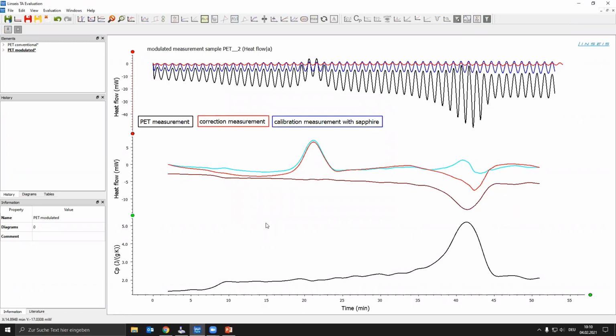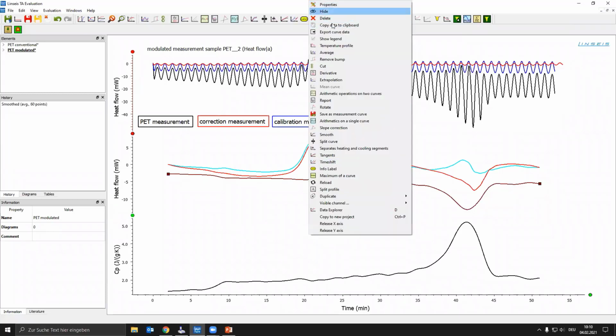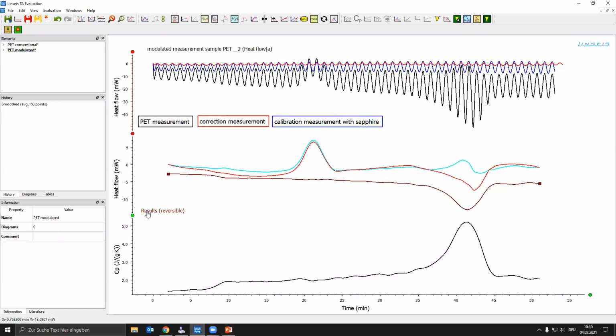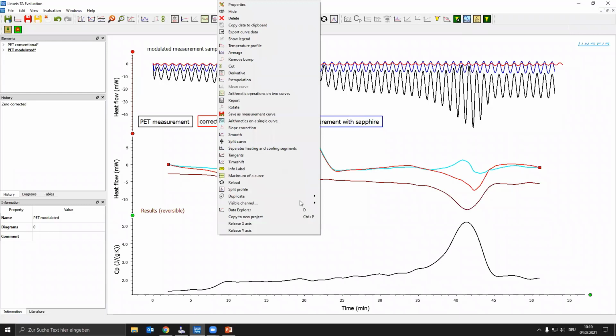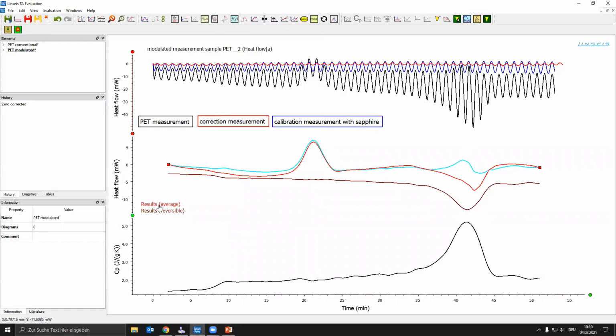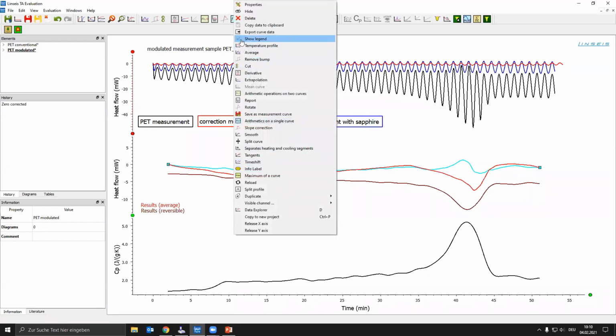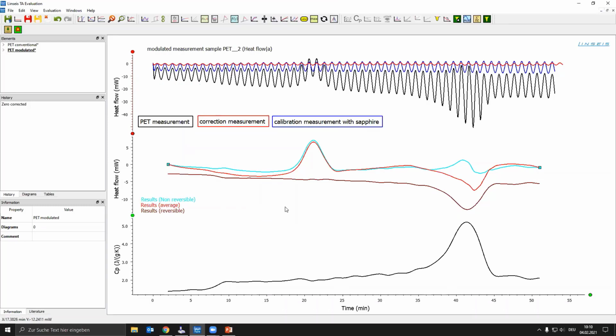And now we can find all the information we could receive with our modulated DSC measurement. So the dark red one is the reversing part, the result for the reversing DSC signal in this case. The red one is the average DSC signal. And the blue one here is the non-reversing part of my DSC signal. And also here you can find the relaxation peak, the recrystallization, and the second recrystallization for the non-reversing part. Of course, again, the glass transition, recrystallization, and complete melting point with the second recrystallization for the complete DSC measurement, and the glass transition and the melting here in the reversing part of our DSC curve.